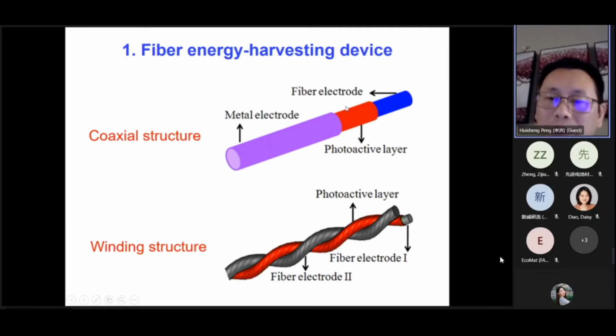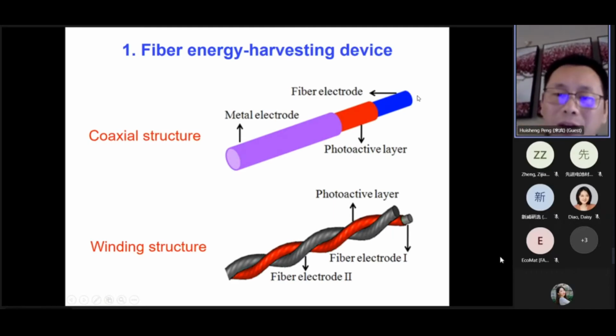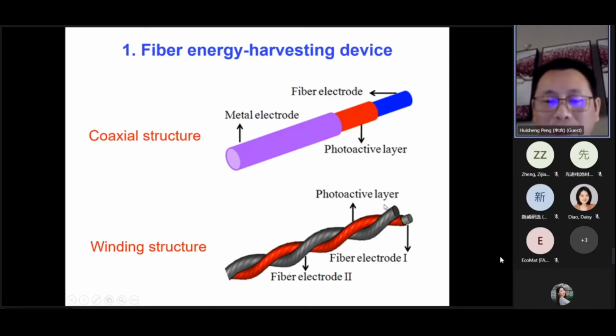Here's one fiber electrode. Then we coat this photoactive layer on the surface, and here is the second electrode. Here we use a metal on the surface, and if you unzip along the left direction, it should look like a structure similar to the planar solar cell. But this second electrode is not easy to make, especially when we want a continuous, very long fiber device. It's very challenging because the film may break since it's very thin. If you make it thicker, it will not be transparent. So there is a balance. So then we try to replace this very thin, unstable electrode with another fiber electrode in a twisted structure. Then it will be much easier for continuous production.